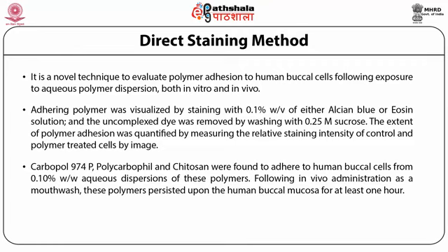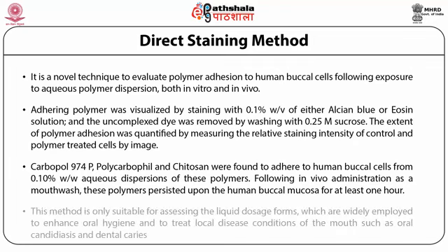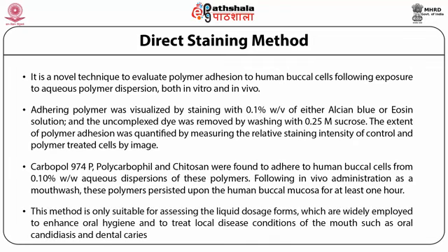Following in vivo administration as a mouthwash, these polymers persisted upon the human buccal mucosa for at least 1 hour. This method is only suitable for assessing liquid dosage forms, which are widely employed to enhance oral hygiene and to treat local disease conditions of the mouth such as oral candidiasis and dental caries.